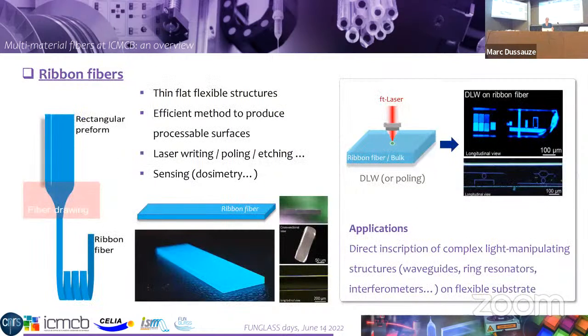Now, if we move to ribbon fibers, the interest came at first a while ago when developing these silver phosphate photosensitive glasses. Those glasses are interesting for laser inscriptions. We were able to make the fibers, but then came out the issue of the curvature of the fiber. Of course there are solutions to solve this issue, but an idea came out: why not develop flat surfaces straight from the beginning? So the question is, can we prepare a flat preform as thin as possible, and are we able, just by pulling on it, to maintain the geometry of the preform in the fibers? So the answer was yes.